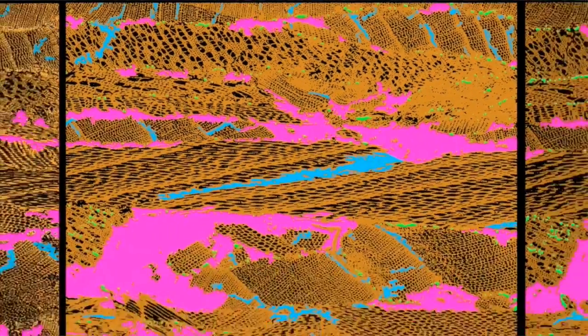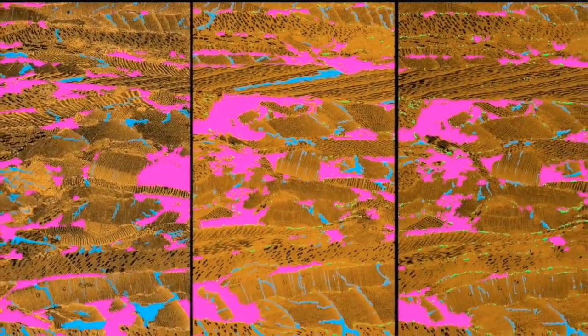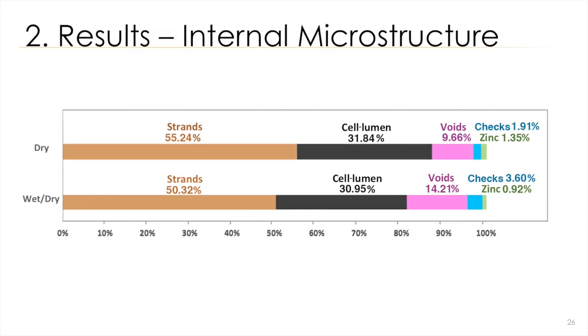So after we measure all of them, with image analysis we can gather data and run a statistical analysis. So from this graph we can see that out of the total sample now, the voids and the checks are a much greater proportion of the overall volume. Checking and voids increased significantly, whereas the strands and zinc decreased significantly. The only phase that did not change significantly was the cell lumen phase.